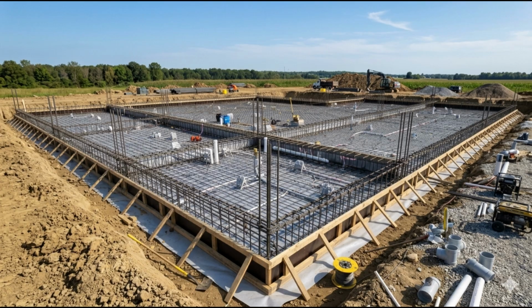He watched the poker vibrators being inserted at regular intervals. The operators seemed competent, withdrawing the vibrators slowly and reinserting at approximately 500 mm centers, which was consistent with the effective radius of a 65 mm diameter poker. He watched the concrete surface being struck off and verified that the screed rails were at the correct level by comparing the finished surface to the level pegs that had been set out before the pour.